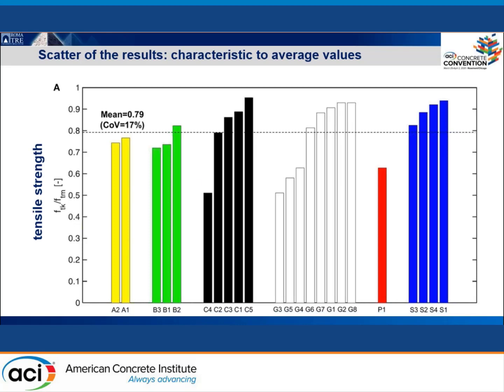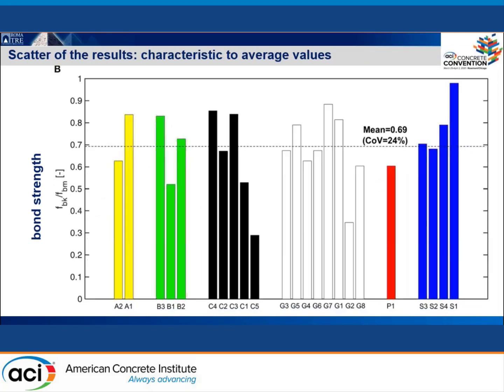But in some systems, as you can see here, in one carbon and one glass system, you have the characteristic value which is about 50% of the average value. And things are even worse in terms of bond properties, because the characteristic bond strength is 69% of the average bond strength, but in some systems, the characteristic strength is about 30% of the average bond strength.